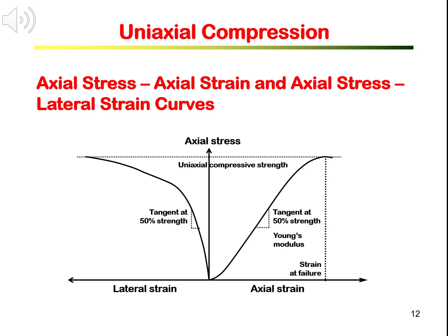Here are the typical axial stress axial strain curve and axial stress lateral strain curve. From the curves, graphically, we can easily determine the peak stress, which is the uniaxial compressive strength. The Young's modulus is a tangent of the axial stress axial strain curve at the 50% stress level, as shown on the right side. From the axial stress lateral or circumferential strain curve, you can also get the tangent of the curve at the 50% stress level on the left. Poisson's ratio is a ratio of the tangent on the right to the tangent on the left.